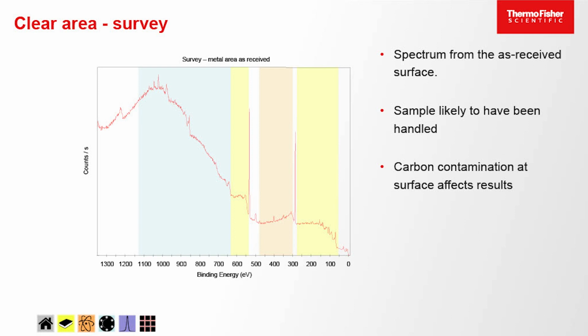Now, if the background's curving down like this, that means that the largest peak next to that is at the surface. And that's where I'd expect, but also now I've got confirmation the carbon is on the top. So this is going to be surface contamination. Everything else, though, I can see the backgrounds are curving upwards, and that means that the photoelectrons for these peaks are having to pass through something else, and so not all of them are able to escape from the surface without losing energy. And so these shapes of the backgrounds are because a lot of the signal is being scattered by hitting other atoms, other electrons in the surface, and losing kinetic energy.